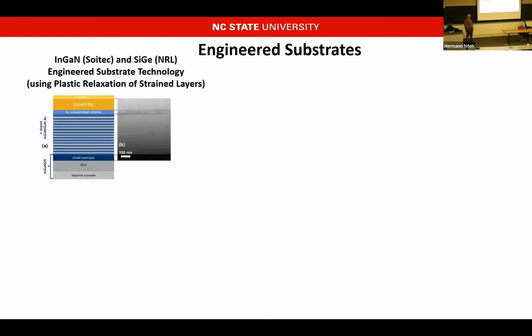The other thing that we're working on is engineered substrates. There's been a lot of what I would say is bad science around engineered substrates, where people have suggested that you could actually use elastic relaxation to generate low dislocation material. But there has actually been some really interesting work where people have used plastic relaxation. And they've done this both in silicon germanium and in InGaN and Soitec.